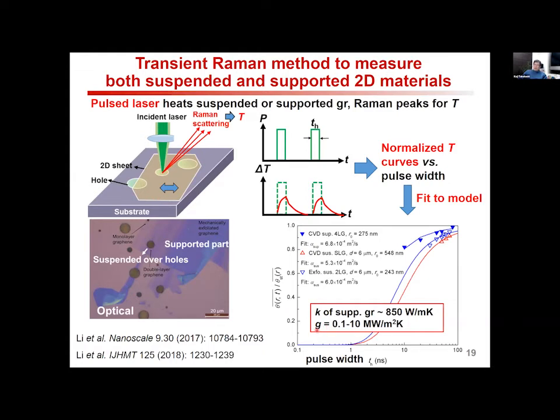And also we obtained the interfacial thermal conductance G, which ranges from 0.1 to 10 megawatts. This kind of interfacial value is very difficult to obtain, but this data is important. So now we can design the thermal management in a chip consisting of this kind of 2D material. So such a measurement technique is very important, not only for the reliability of CPU, but also for the reduction of the electricity used for cooling.